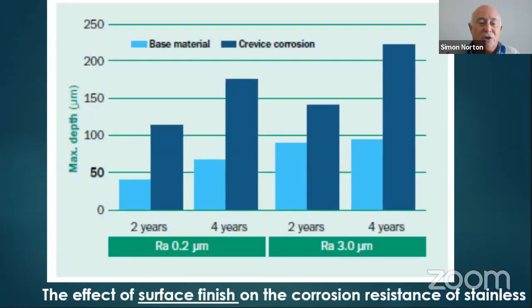This particular graph shows merely that if you've got a surface roughness of 0.2 microns and a surface roughness of 3, if you see where my cursor is at the bottom of the screen, and look at the depth of corrosion that's occurred, you can see that if your surface roughness is very fine, you get less corrosion than if your surface roughness is rough, or a higher value. So you've got an order of magnitude from an Ra of 0.2 microns to an Ra of 3 microns. And you can see after 4 years, there's a difference between the two corrosion rates, the maximum depth to which corrosion has occurred.